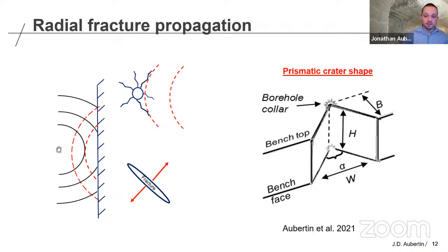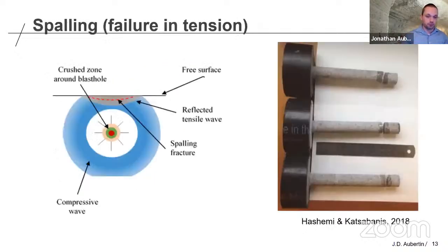This behavior is very critical to how the cratering process takes place, because the geometry of radial fractures and the way they expand reaching the free surface yields a generally almost prismatic crater shape. And this prismatic, this triangular cross-section of the crater is very fundamental to all modern notions of blast designs, and all our guidelines and rules of thumb are related to some extent to that kind of dimensioning of the crater.